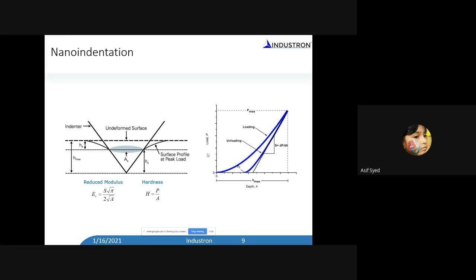You are taking a probe and you know the shape of this probe. I said a 3-sided pyramidal probe, but the tip end is something whose shape you don't know. It's normally spherical. But by doing calibration on a known sample, for example fused quartz, for which the modulus of the material is known, you do an indent and measure the stiffness from the unloading curve of the load displacement curve. You load and unload, this is the typical load displacement curve. From the unloading curve, this is the load, this is the displacement, and if you take the slope, it's basically stiffness, right? So you measure the stiffness from this unloading curve.